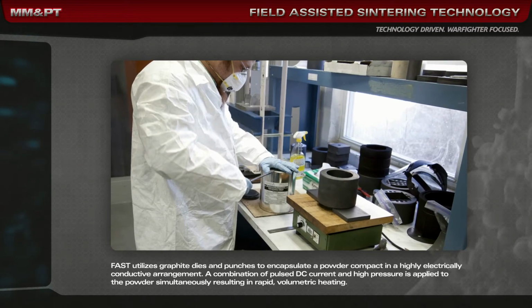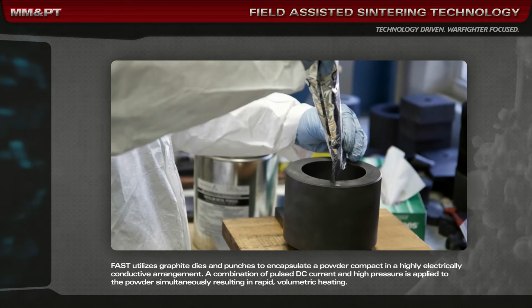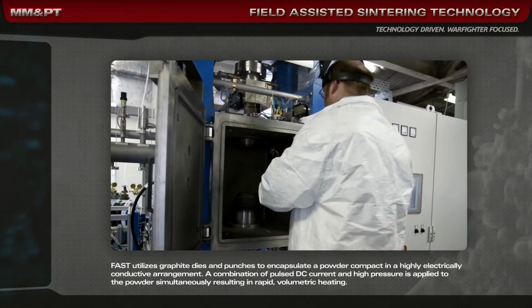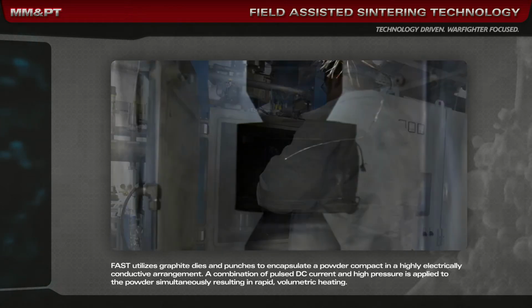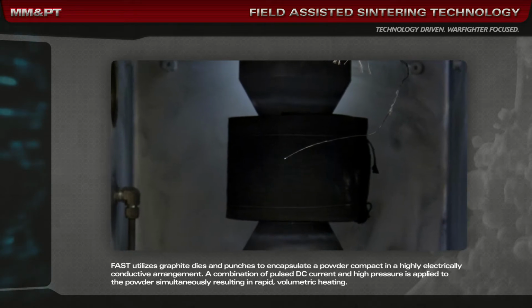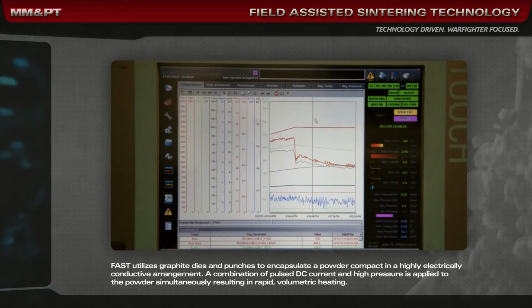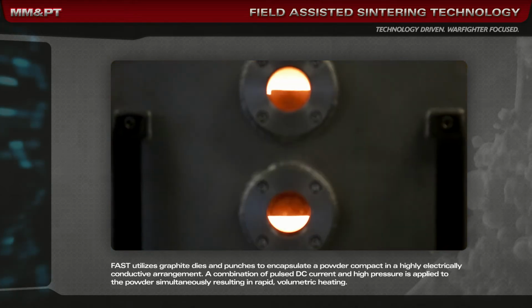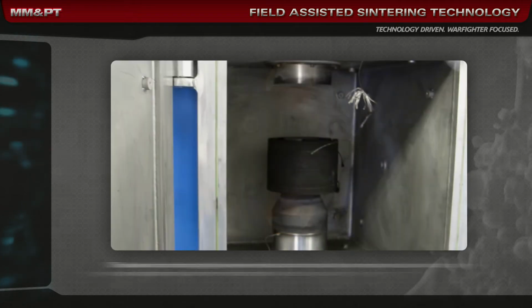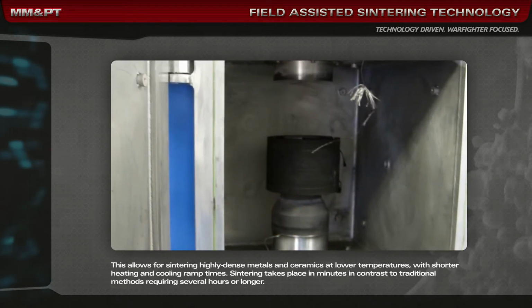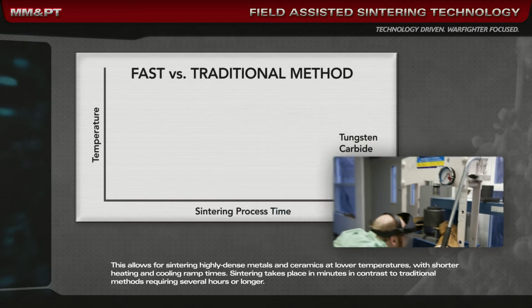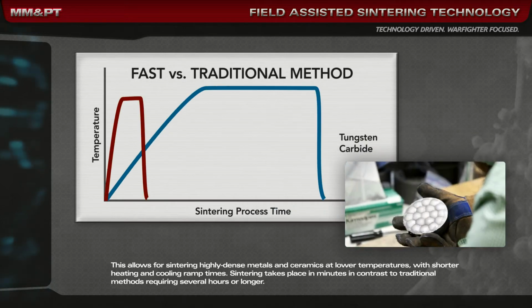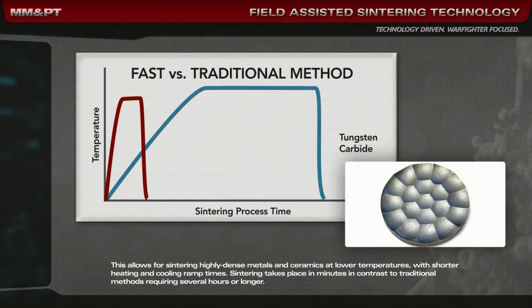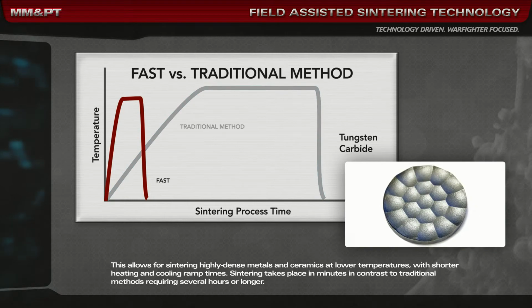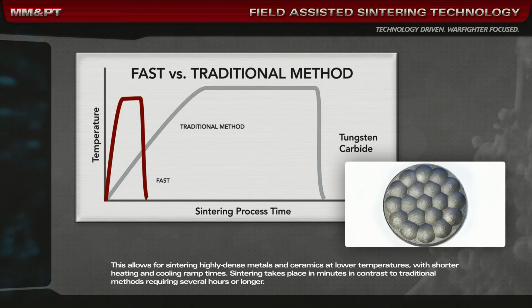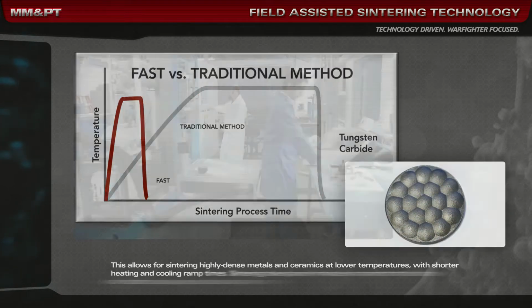FAST utilizes graphite dies and punches to encapsulate a powder compact in a highly electrically conductive arrangement. A combination of pulsed DC current and high pressure is applied to the powder, simultaneously resulting in rapid volumetric heating. This allows for sintering highly dense metals and ceramics at lower temperatures, with shorter heating and cooling ramp times. Sintering takes place in minutes, in contrast to traditional methods requiring several hours or longer.